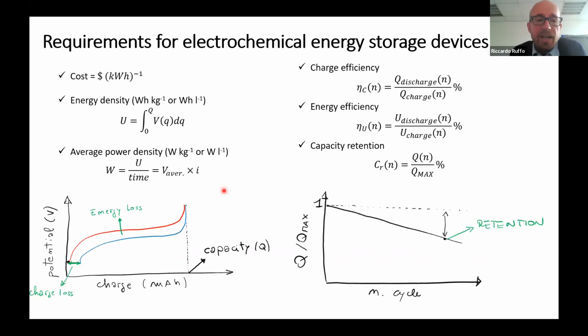So in this case, we can have 2 losses. One is due to the fact that you are not able to use all the materials that you spend during the charge, during the discharge, so you have charge loss. And the second point, which is a thermodynamic limit of our system, which is due to the second thermodynamic law, is the energy loss, so the difference in the areas of the 2 charges.